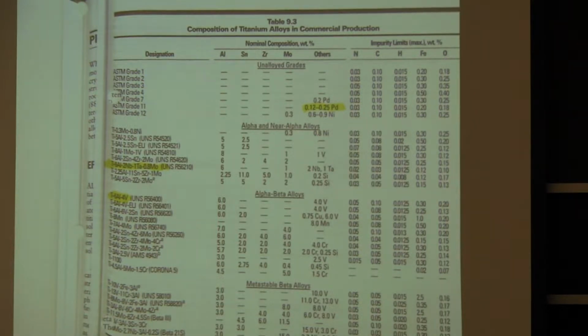Oxygen does lower the toughness of the titanium, but it increases the strength, just like carbon does to steel or iron. We have these grades that have some palladium in them. Why would you put palladium? Palladium is a precious metal like platinum, with a similar price. Anybody know why we put palladium in titanium? In very caustic solutions like pH 10 or greater, you improve the crevice corrosion resistance. There are only a few situations where titanium will corrode, but at very high pH it's crevice corrosion.